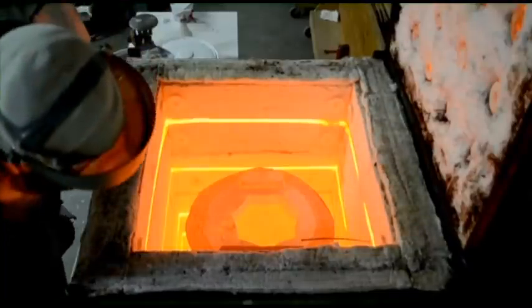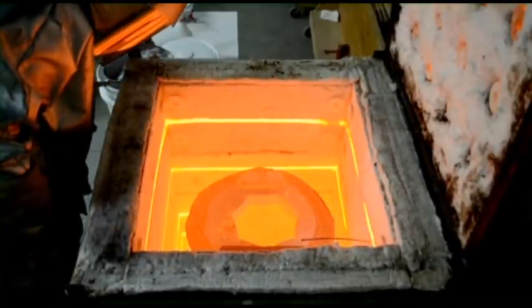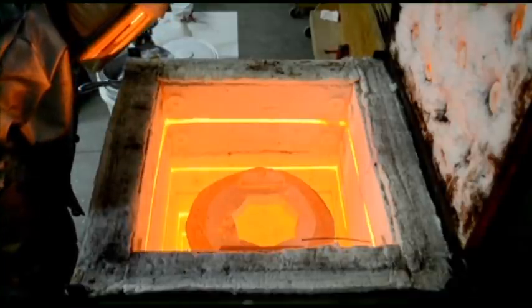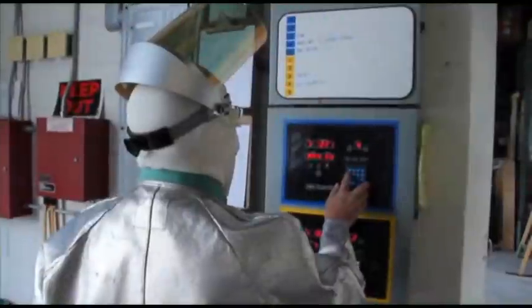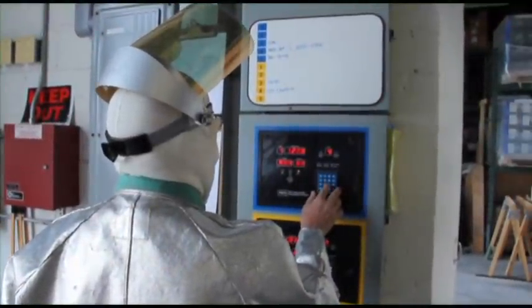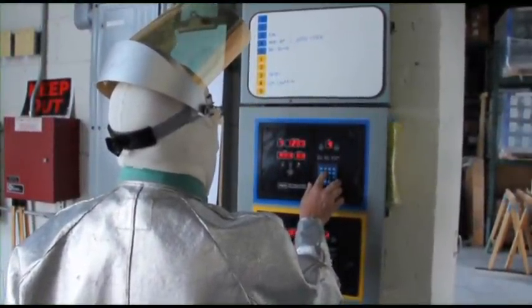The amphora has been in the kiln for about 14 days. The full firing cycle is approximately 14 to 15 days, with a couple days to bring it up in temperature, a day for it to melt the glass, and then 12 to 13 days for it to come back down to room temperature. The cooling of the work is very specifically controlled by the computers.